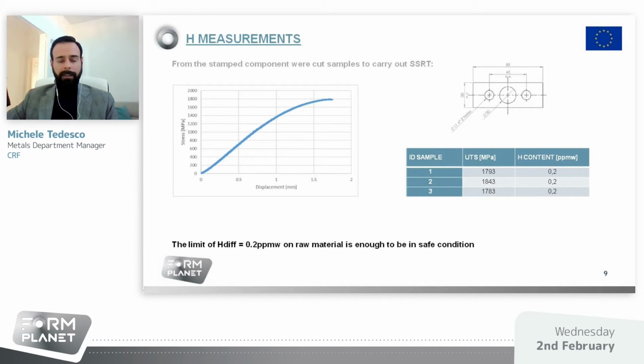The result was very positive because the mechanical properties still remain the same as the virgin material, and so this means that the material, also in the worst case, is in a safe condition. For this reason, the Material Engineering of Stellantis gave the validation of Usibor 2000 to Arcelor.